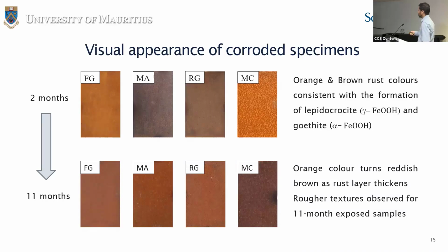After 2 months of exposure, a difference in appearance of the specimens exposed at different sites in Port Louis and the mid-island atmosphere can be observed. The orange and brown rust colors are consistent with formation of the lepidocrocite and goethite rust phases. After 11 months of exposure, as the rust layer thickens, there are rougher textures on the surfaces and the rust color grows darker.